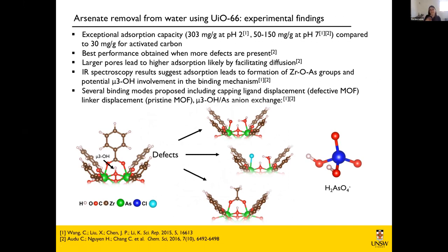Now, these studies are extremely interesting because they also look into how the defects specifically affect the performance. And they found that the more defects, the better. And also the bigger the pores in the MOF, which can be achieved in different ways, the better the performance. The nice thing from the computational perspective is that these studies also use some IR spectroscopy to actually figure out how the arsenic is interacting with the MOF.